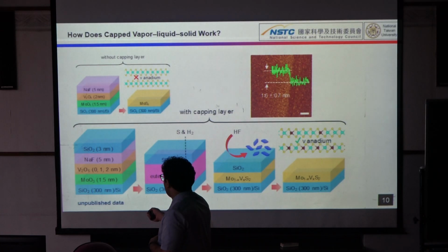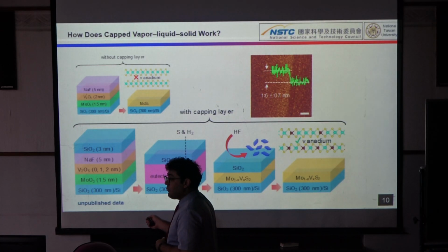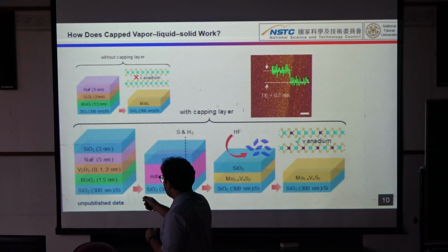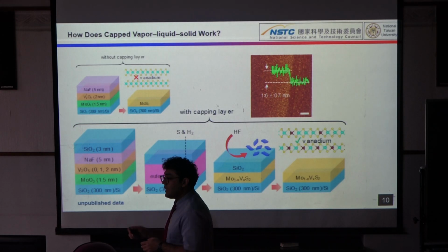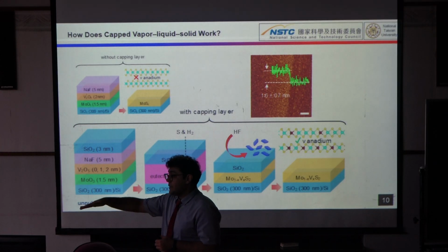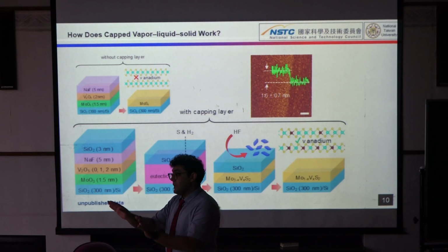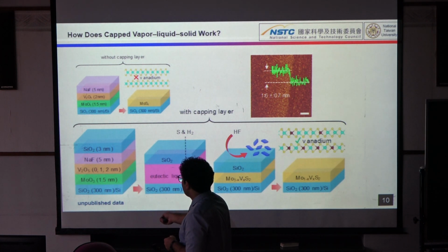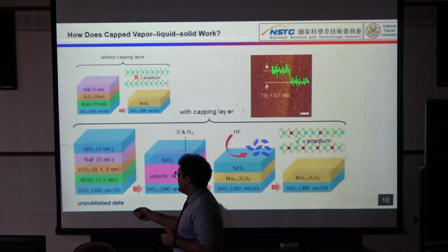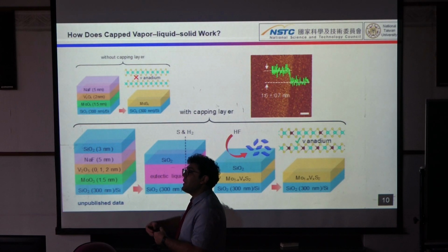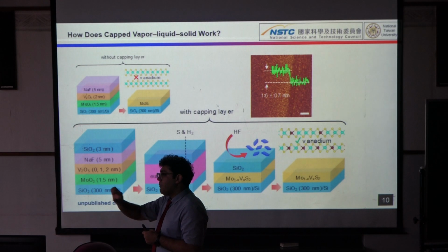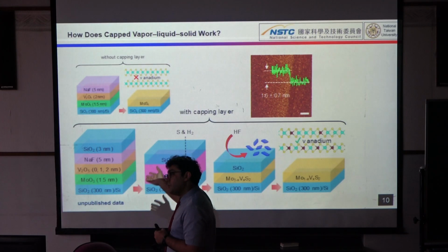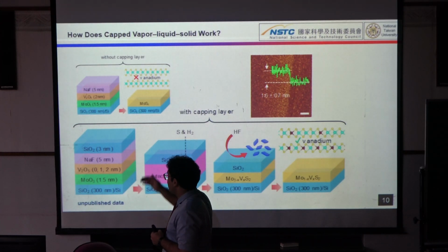You mean this one? Then you need the thickness, right? For the thickness, we use ALD to grow the film. For each layer, I should say that we put a lot of time into making it very flat. If it is not flat, it will not give you a good result. This kind of growth actually started about 5 years ago, with each student coming to the project. The first student worked on MoS2, so she could grow 1.5 or 1 nanometer MoS2. And the second student wanted to grow vanadium oxide and then sodium fluoride.